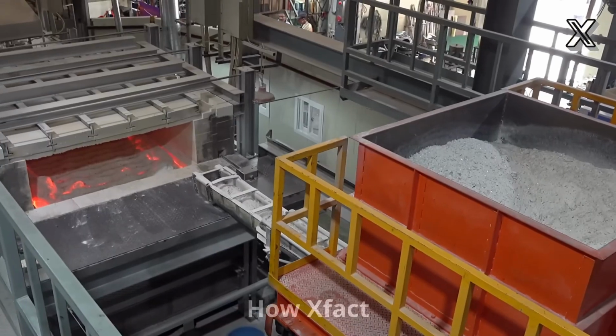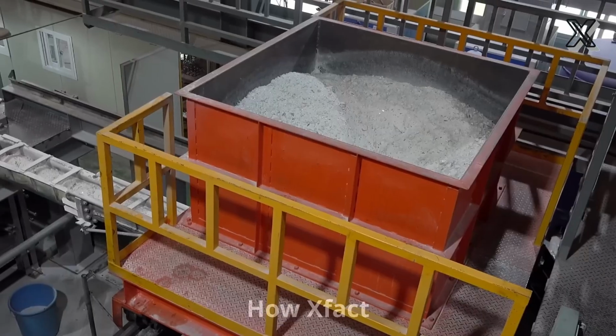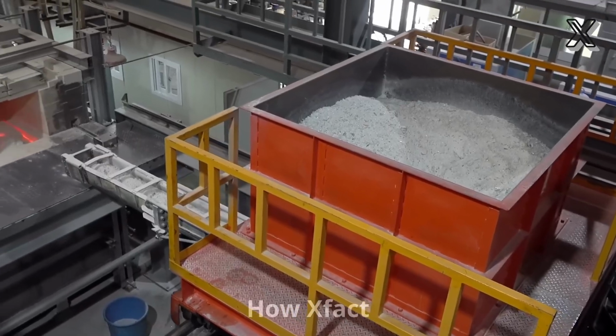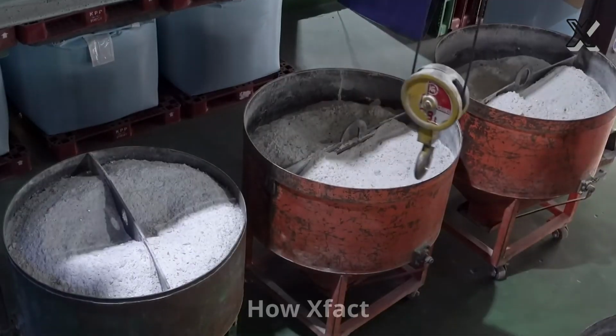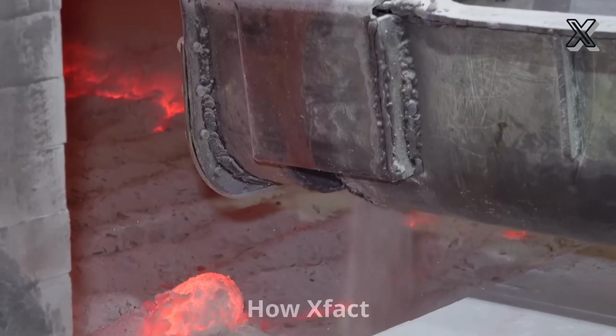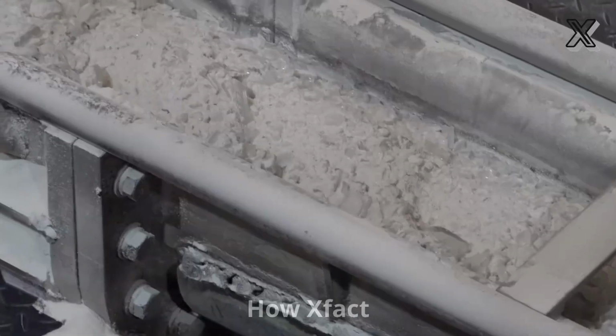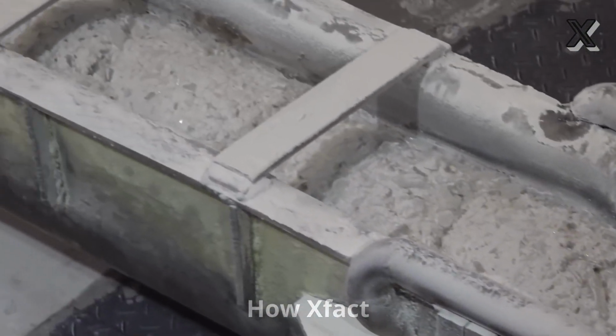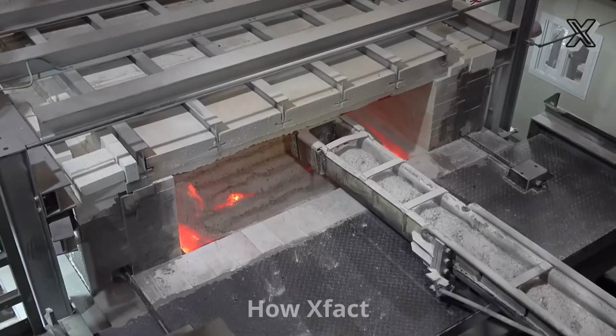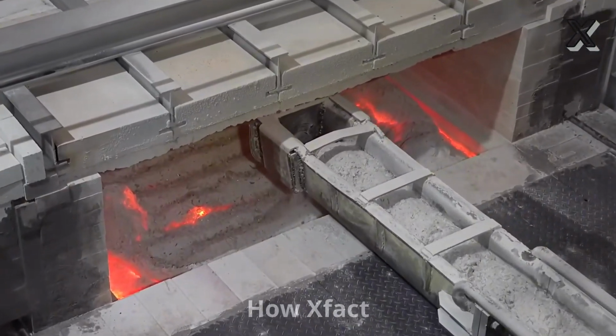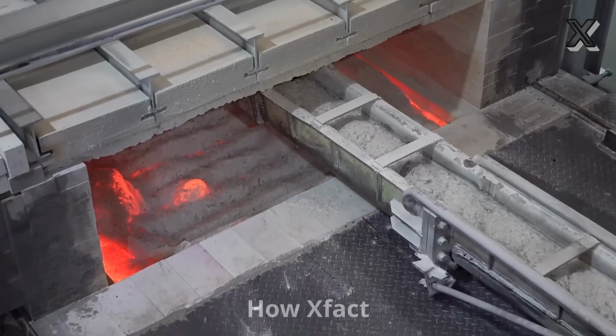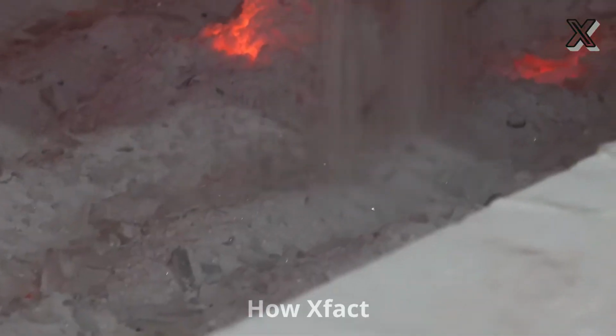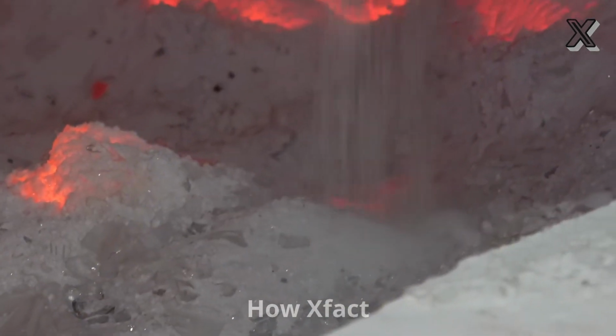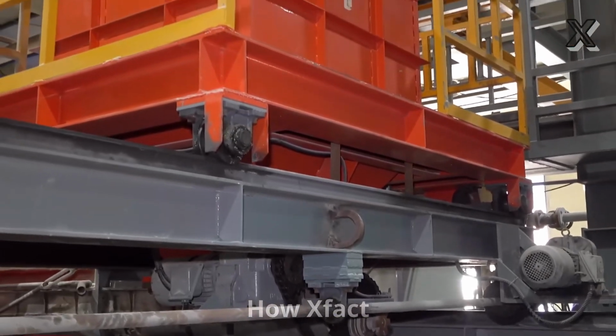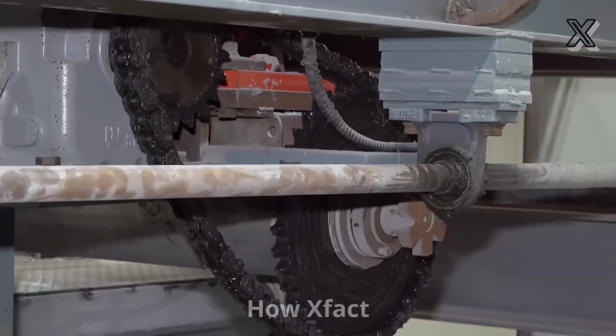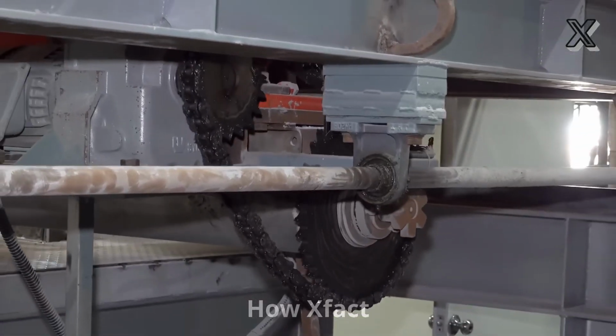Technicians monitor the entire process from a control room, adjusting temperature, airflow, and timing with extreme precision. Inside the furnace, the material slowly transitions from a grainy mixture to a smooth, honey-like flow. Workers nearby must wear fire-resistant suits, heavy visors, and Kevlar gloves to withstand the radiant heat that pours from every opening. For nearly 24 hours, the molten material is held at high temperature, allowing trapped gases to escape. This stage is crucial. A single bubble or impurity can weaken the final glass.